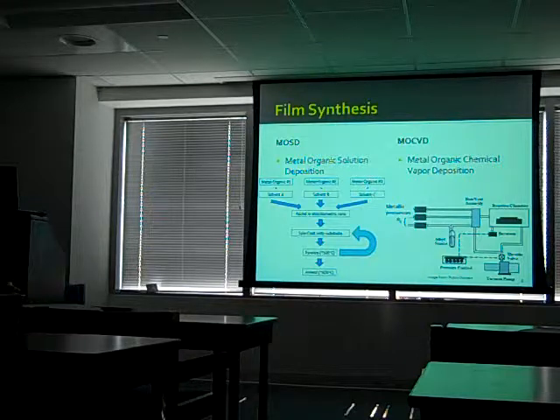They're dissolved in their respective solvents and then combined in the desired stoichiometric ratio. The solution is then spin-coated onto a substrate. The substrate rotates at about 3 to 4,000 RPM, and then subsequently is heated to 300 degrees C to remove any organic addenda. The spin coat and pyrolyze step is then iterated as many times as is needed to get the desired thickness of your film. Finally, once you have the desired thickness, it's annealed in ambient oxygen, anywhere from 600 to 800 degrees C.